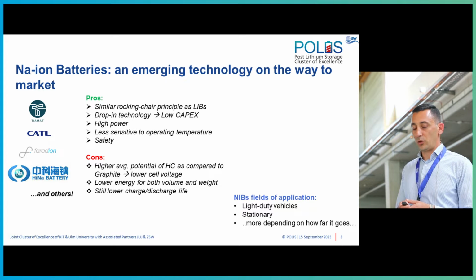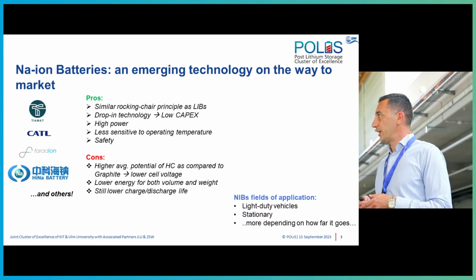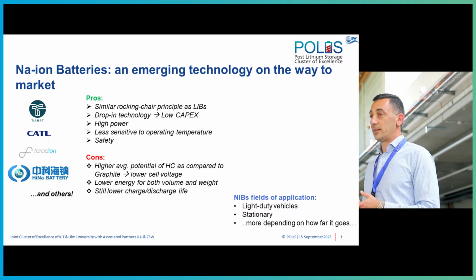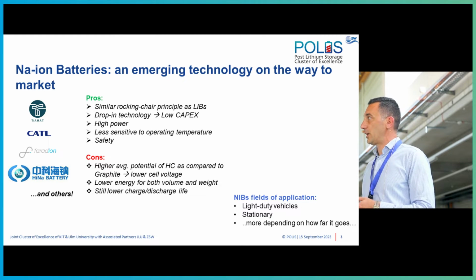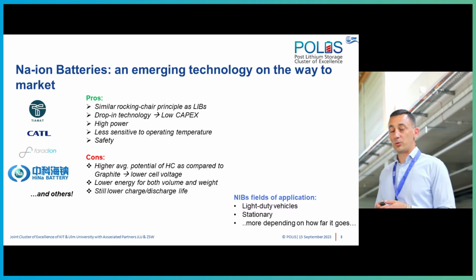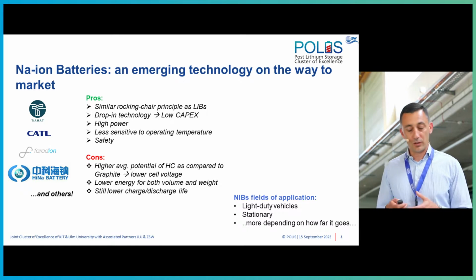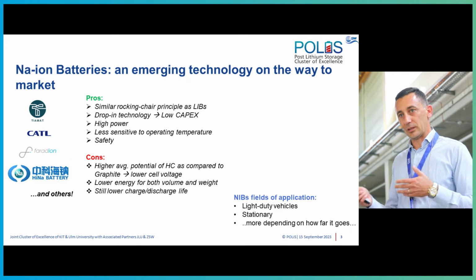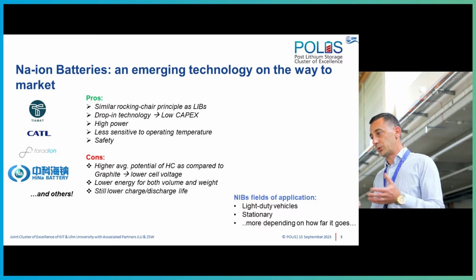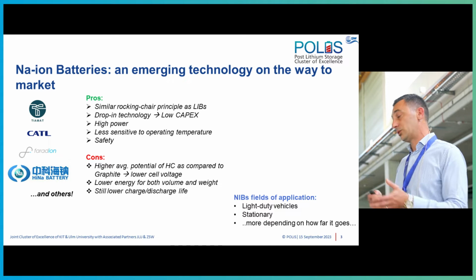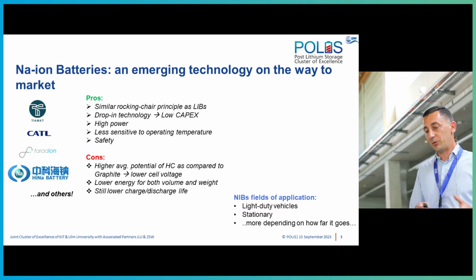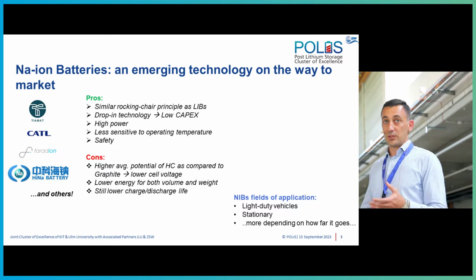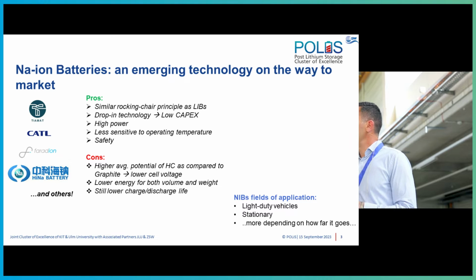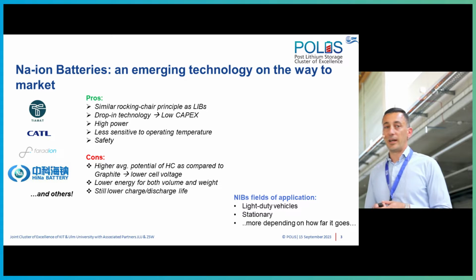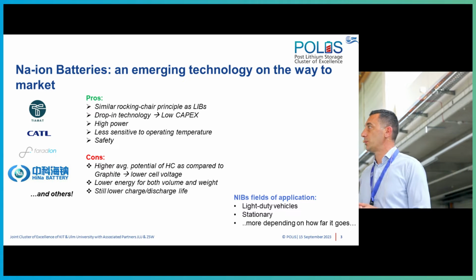What sodium-ion has in its pocket, let's say, is that it is supposed to have high power and be less sensitive to operating conditions. We all know that this is a big issue for lithium-ion batteries. Going to particularly low temperature will lead to lithium deposition, then dendrite growth, and then safety issues. If you go to higher temperature, you start degrading the cathode material. So probably sodium-ion batteries have an edge in that respect, in that KPI.